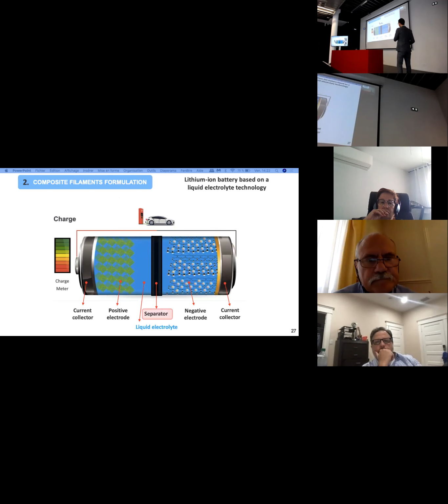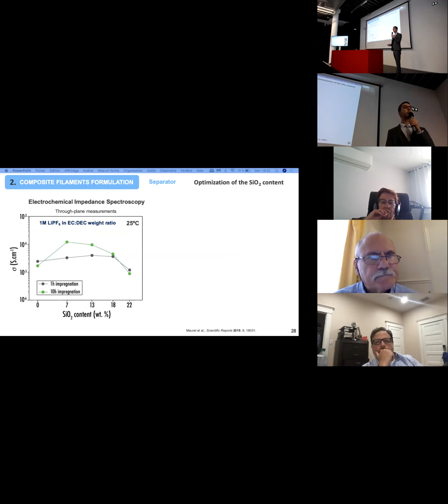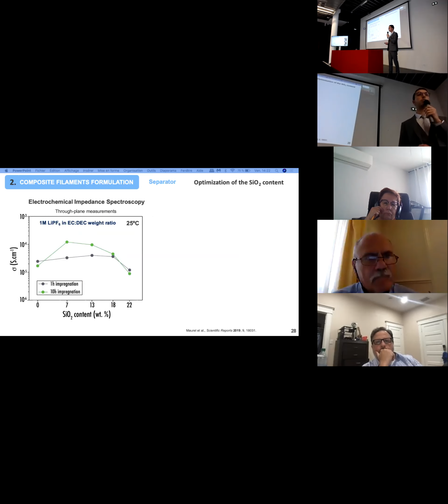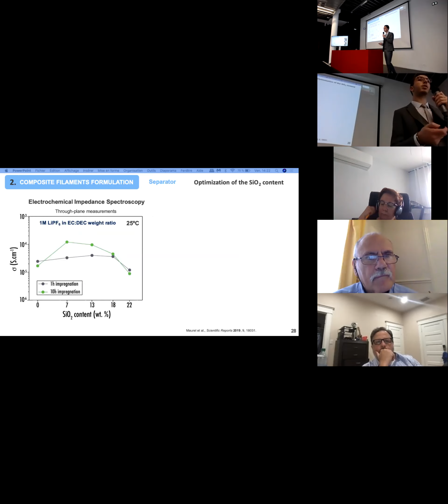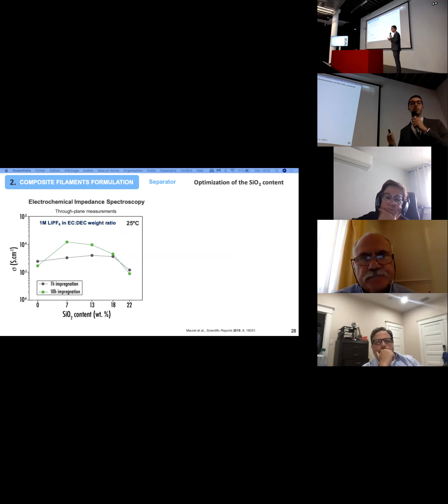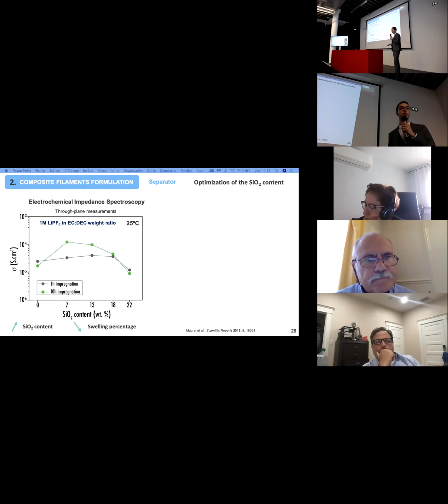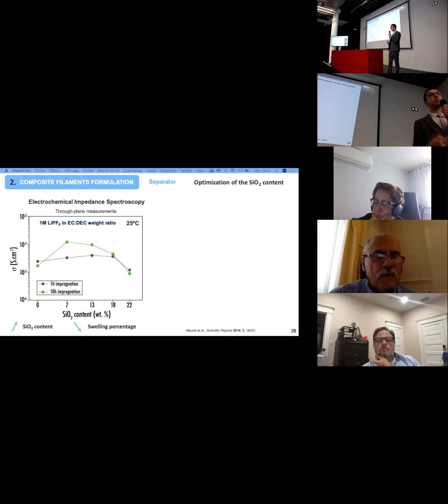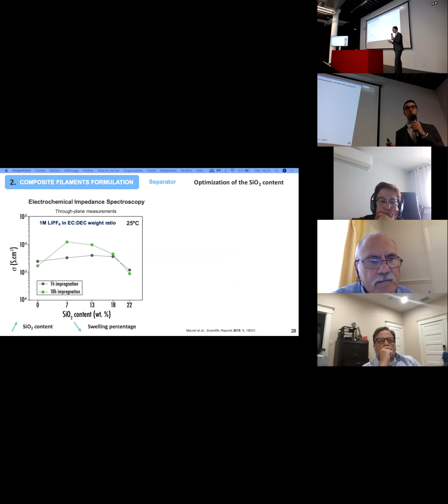And we also tried to develop a filament for the separator. Starting from a pure PLA filament, we tried, in order to increase a little bit the liquid electrolyte impregnation, to implement some silica particles in the filament. By increasing the silica content, we saw that the swelling was decreasing, which makes total sense because the polymer matrix is the one that is prone to be solvated with the liquid electrolyte.